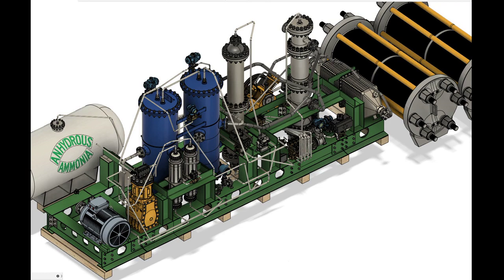Thankfully for ammonia plant designers, nitriding need not be overly concerning, since the ammonia reaction rate is so low, only at best 18 to 20% of the ammonia is converted per pass. This low concentration of ammonia keeps the nitriding rate to acceptable and manageable levels. Nitriding becomes a serious issue when NH3 concentrations exceed 50%. This may place limits on the resurrection of the Claude process unless higher nickel fraction alloys can be used.